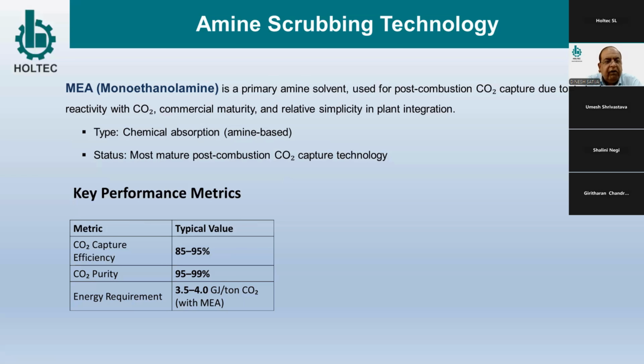So this is finding more acceptability with the cement industry. The typical process is chemical absorption, amine based, and the status is the most matured post-combustion CO2 capture technology. The key performance metrics: CO2 capture efficiency could be around 85 to 95%, and CO2 purity is 95 to 99%. It is again energy intensive, 3.5 to 4 gigajoule per ton of CO2 captured. That is the energy requirement.